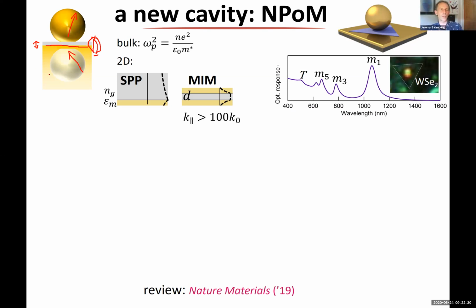That's a very good question. We'll get to it a bit later, but essentially what's important in the gap here turns out to be the polarizability in this vertical direction. So when I put, say, graphene against the gold, you might ask, doesn't the gold completely change the properties of the graphene? The answer seems to be no, and it's because essentially there are S-like electrons in the gold and P-like electrons in the graphene. That's the best way I can try to explain it.